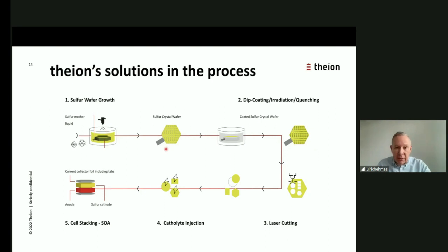Then we take that out and we dip coat it in a very special but cheap material, in order to protect the surface against these polysulfide shuttles, so avoid corrosion. This material is then cross-linked with a special irradiation process. Then we cut it to the size of the electrode we need in the cell. And then we add a catholyte, which is very beneficial for the cycle life as well, and helps to extend the cycle life together with the anode.